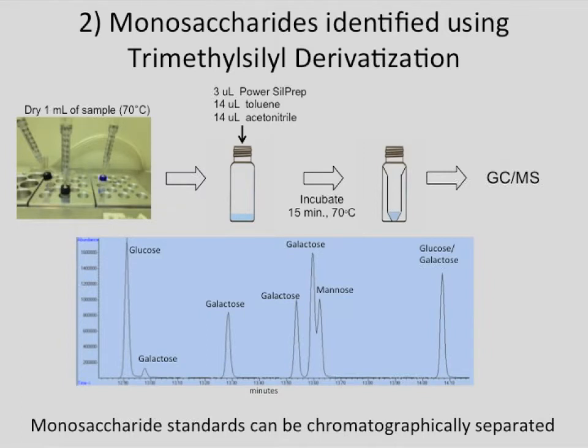So that drying of the sample to look for the sugars looks a lot like this, where these actually should have caps on them. We dried the samples out, added some acetonitrile, toluene, and power sil prep. The power sil prep does the trimethylsilylating. We incubate it for 15 minutes at 70 degrees Celsius, and then inject it into the GCMS.